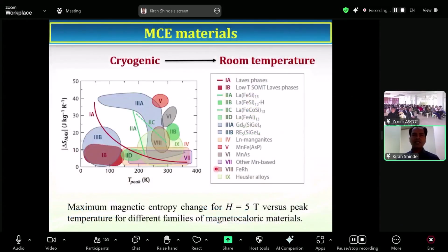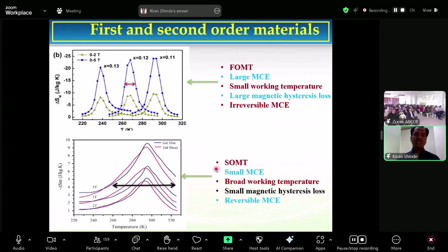Here we can see the magnetocaloric materials with respect to their Curie temperature and respective magnetic entropy change when we apply the magnetic field of 5 Tesla. So these materials are divided into two groups: first order phase transition and second order phase transition materials. First order phase transition materials have some drawbacks when we are using this kind of material for the application purpose. Even though they have high magnetic entropy change, the working temperature range is smaller compared to the second order phase transition material. Another drawback with this first order magnetic transition material is that they have the magnetic hysteresis loss.